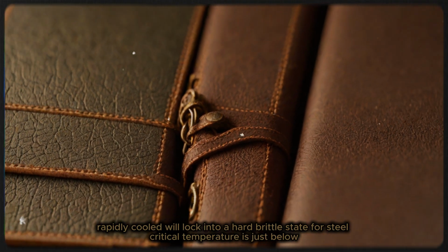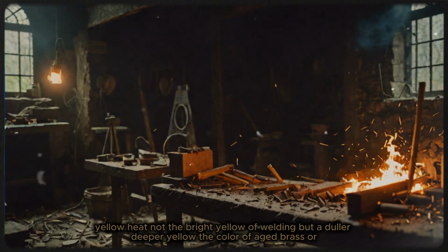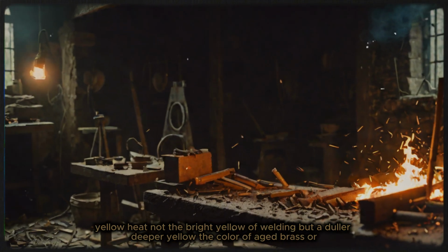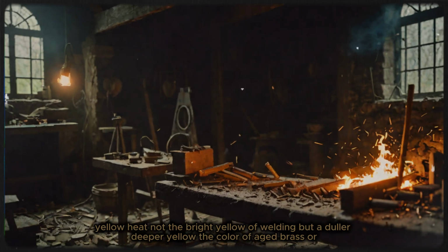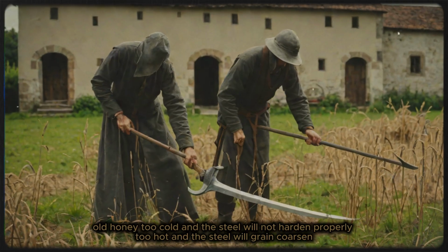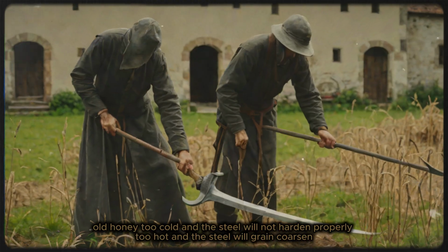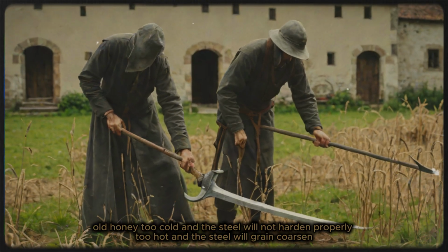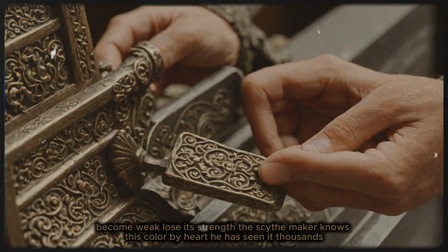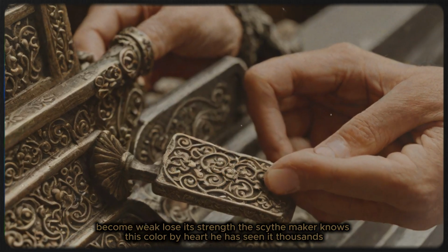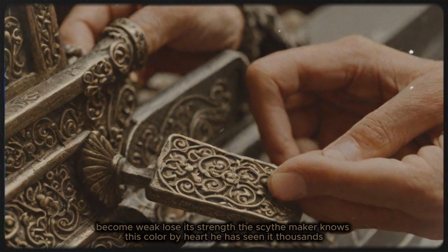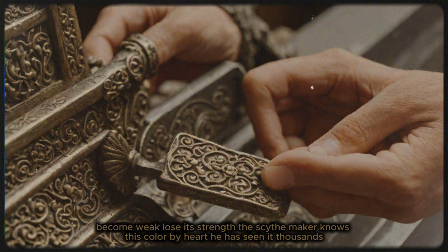For steel, critical temperature is just below yellow heat, not the bright yellow of welding, but a duller, deeper yellow, the color of aged brass or old honey. Too cold and the steel will not harden properly. Too hot and the steel will grain coarsen, become weak, lose its strength. The scythe maker knows this color by heart. He has seen it thousands of times.